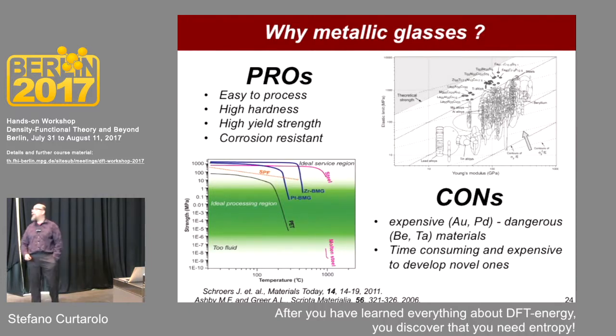What are metallic glasses? Metallic glasses are metals. You mix metals and you cool them very quickly, and instead of forming a crystalline phase, they form an amorphous phase. Mechanically, they are marvels, right? They are Superman, they are superstars. Why? Because they are easy to process, high hardness, beautiful corrosion resistance. You know where corrosion starts? On a surface, on a defect, a dislocation. If your system is a glass, it's all defects. So it's impossible to create defects on a system that is all defected. It is just defected by construction.